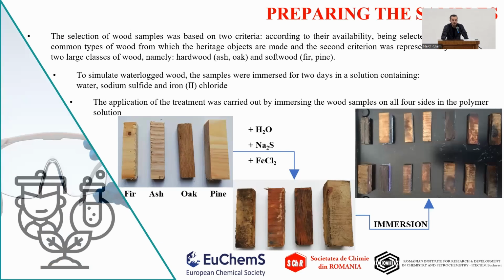To apply this material, we need to prepare some samples. For this, the selection of the wood samples was based on two criteria. The first was their availability, selecting the common types of wood from which heritage objects are made. And the second criterion was the two large classes of wood, namely hardwood, for which we selected ash and oak, and softwood, for which we selected fir and pine.